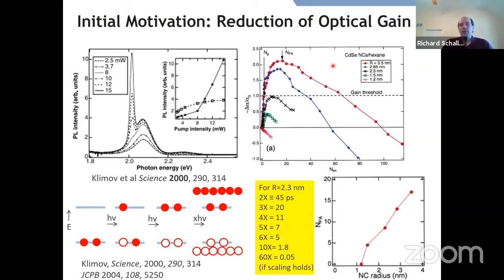But then, what was motivating me to try to get into some of these understandings of phonons is a subsequent observable that was also shown, where if you look at optical gain, and I won't get into this axis too much, the idea here is that as you cross this value of 1, when you're putting a pump beam in and then probing at the transition energy of the conduction band, valence band gap, you start to see more light output come out relative to the probe light that you sent in. And so that means you're getting optical amplification.